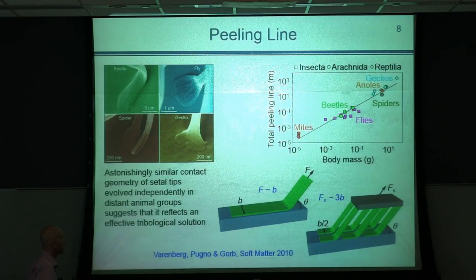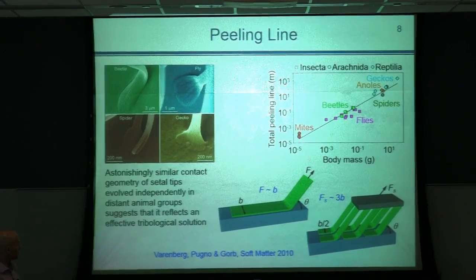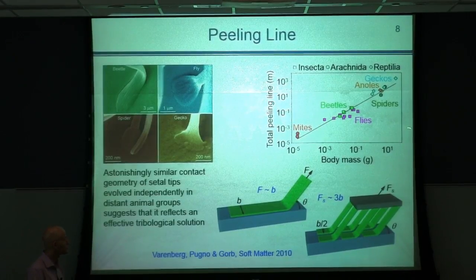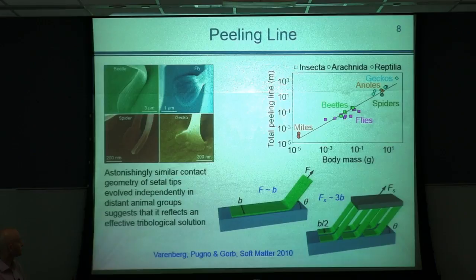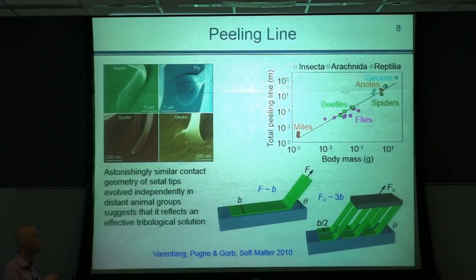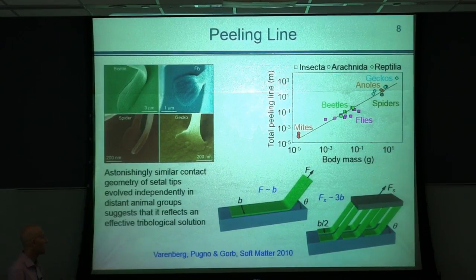And these are results that represent total peeling line length, the sum of width of all contact elements in about 20 different animals, represented as a function of their body mass. You can see here that body mass ranges within more than 4 orders of magnitude, from several micrograms for mites to over 100 grams for gecko, and total peeling line ranges within 8 orders of magnitude, from several micrometers for mites to over 1 kilometer for gecko. And clearly you can see that there exists a good correlation between these two parameters.